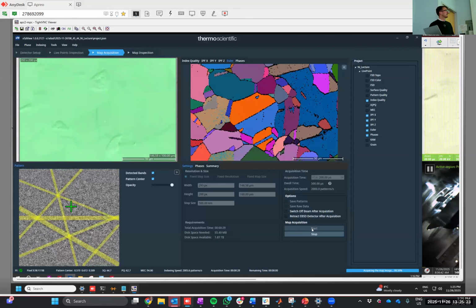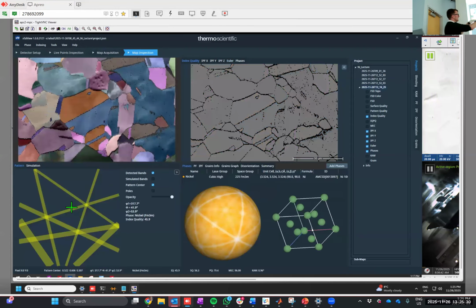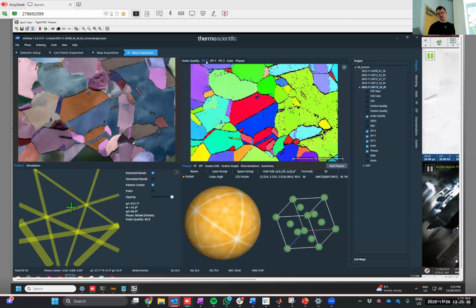The system is beautifully set up to do this nicely. So this is then doing a little bit of maths behind to show us some stuff. This is not cleaned up data. It's not quite in focus because it drifted, so grain boundaries look a bit wide. But we can then see those different maps as presented in the microstructure.